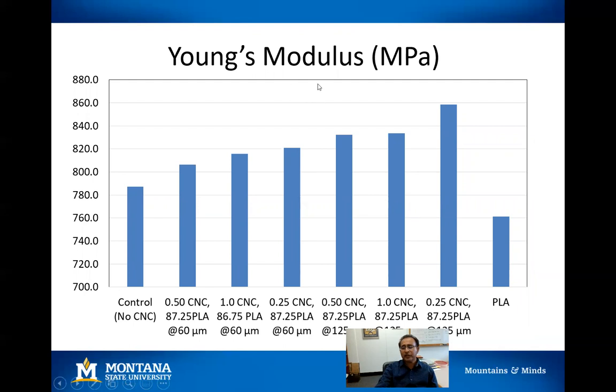So the next property is Young's modulus, or the stiffness. And in this, we can see there is a control with no CNC. And as we add CNC, there is an increase in the Young's modulus. And this is a PLA. So PLA commercial has much lower stiffness, but all other formulations showed a higher stiffness with the CNC and DDGS.